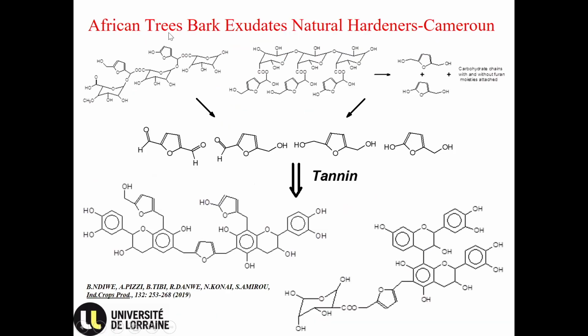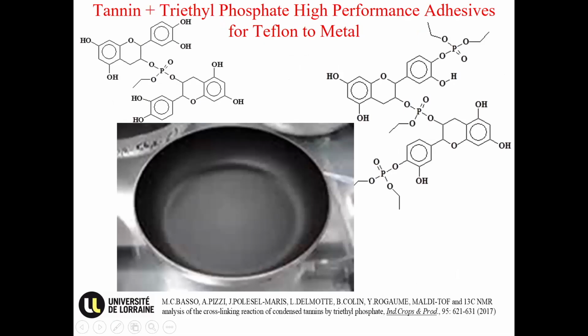Most interesting is something that came from Cameroon. African tree bark exudates used as natural hardeners of tannin. The exudates, obtained like you obtain latex from a tree, from a number of African trees, contain furanic moieties attached to them. And when you press this material together with a tannin, for instance, you detach some of the furanic moieties from this hardener, and they harden the system, giving a mixed carbohydrate and tannin system. This works quite well. The people in Cameroon are still working on it, and it is a very easy, very feasible system that is totally bio.